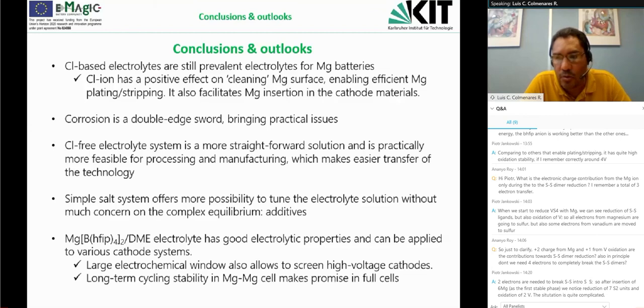Why do some no-chloride DME-based electrolytes have anodic stability probably far above the anodic stability of the solvent, like DME? For example, 4.5 volts versus magnesium for a magnesium borate electrolyte in DME.